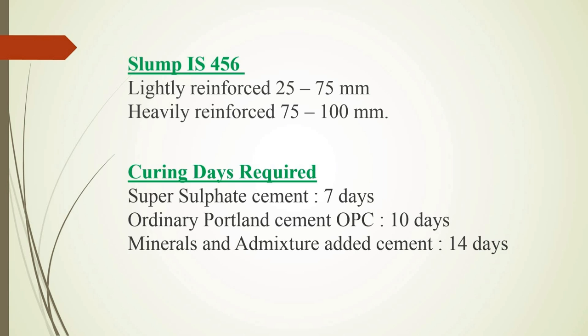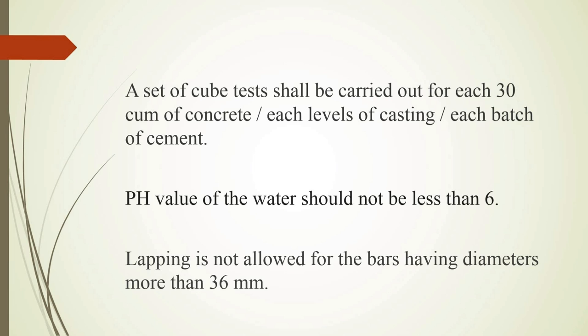Curing is most important for concrete. Super Sulphate cement requires 7 days of curing. Ordinary Portland Cement (OPC) requires 10 days of curing. Minerals and admixture-added cement content requires 14 days of curing. A set of cube tests shall be carried out for each 30 cubic meters of concrete, or each level of casting, or each consignment of cement.